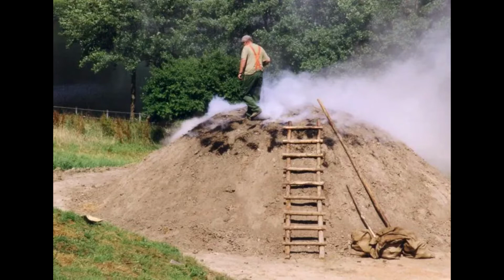The fuel ignites and begins consuming the oxygen from the interior of the kiln, both heating the wood but also stealing the oxygen the wood needs to combust itself. The charcoal burner, often called a collier, before that term meant coal miner, it meant charcoal burner, manages the charcoal pile through the process by watching the smoke it emits and using its color to gauge the level of combustion. Dark, sooty smoke would indicate that the process wasn't yet done, while white smoke meant that the combustion was now happening clean, indicating that the carbonization was finished.